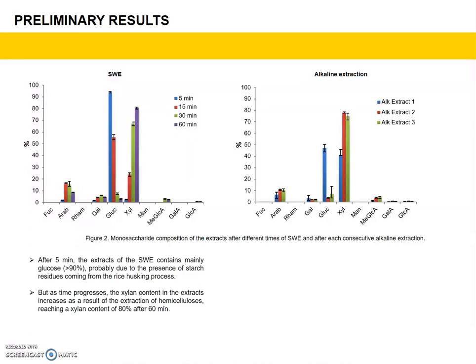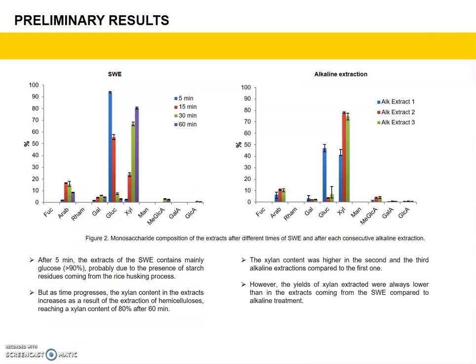After 5 minutes, the extract of the subcritical water extraction contains mainly glucose, probably due to the presence of starch residues coming from the rice husking process. But, as time progresses, the xylan content in the extracts increases as a result of the extraction of hemicelluloses, reaching a xylan content of 80% after 60 minutes. Likewise, the xylan content was higher in the second and the third alkaline extraction compared to the first one. However, the amount of xylan extracted was always lower in the extracts coming from the subcritical water extraction.